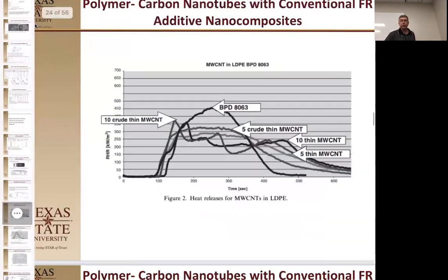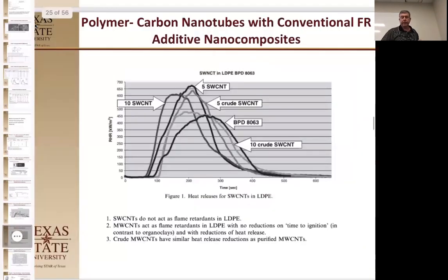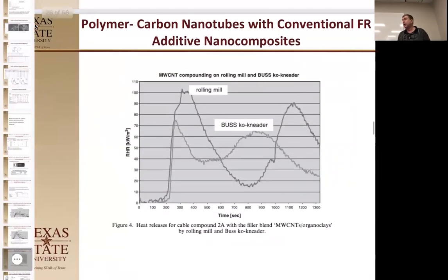It was, all of them were less than the pure polymer. And they all seem to have a little dip and then an up, except for this one, the 5 to 8% seem to have a nice flat curve. So it seems that the processing of this is going to be neat. And if you think about it, a rolling mill is just kind of like this cup mixing like this for a while. And the co-kneader is probably something similar, but has a different blade design. So you get a little more shear.